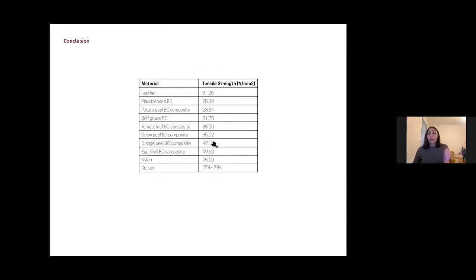However, the composite materials still maintain a higher tensile strength than leather. If we look at the blended bacterial cellulose, in comparison to the not blended one, it is just a little bit weaker. However, adding the additives did make it regain its strength. So at this point, the null hypothesis was rejected and my hypothesis was accepted due to the fact that the food waste additives did increase the material properties of the blended bacterial cellulose.